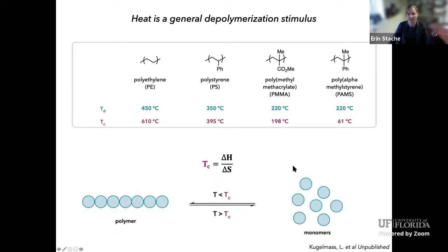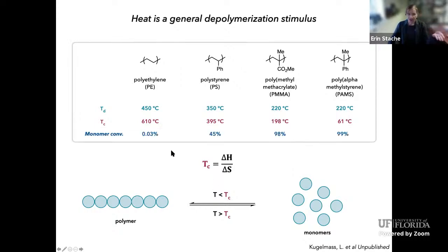And so this is how we're starting to think about depolymerization of polymers. Can we use heat as a stimulus to do this? So it turns out if your degradation temperature is far below your ceiling temperature, you're not really going to push this back to monomer, because you're just going to keep breaking bonds in the backbone, and you're just going to get a lot of side reactions. But as you get closer to merging these two numbers, as your ceiling temperature gets closer to your degradation temperature, you start to get monomer back. So with polystyrene, you can get almost 50%. And as you move to these other polymers, you can get almost quantitative return of your monomer if you heat these high enough.